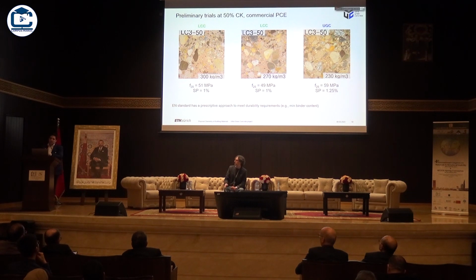And these are some of the mixtures that we have been working on. So the first two, based on this arbitrary definition that I proposed, would be low carbon concrete. The last one would be an ultra-green concrete. You see the strength there, the binder content, and these were all made with LC3-50. So we're not even going yet into the direction of reducing the clinker factor even lower.